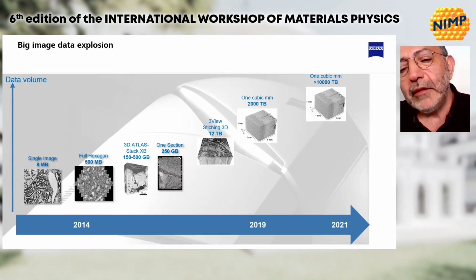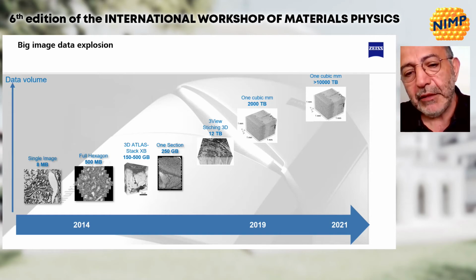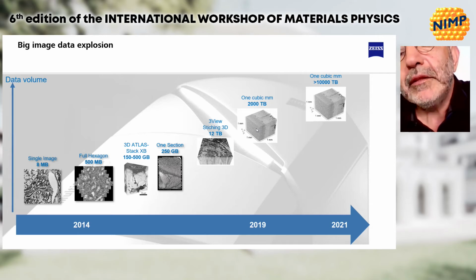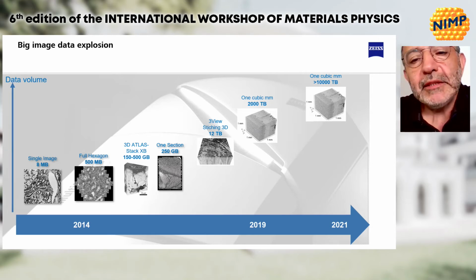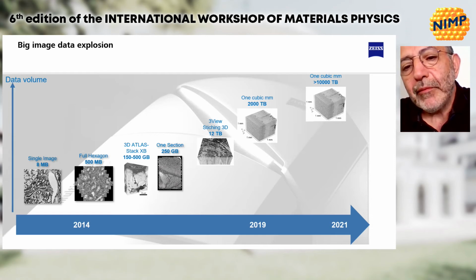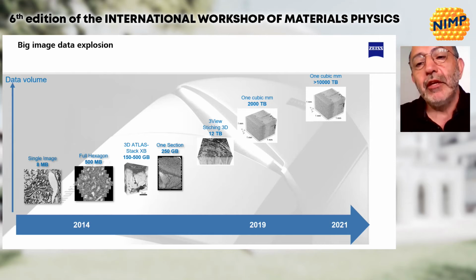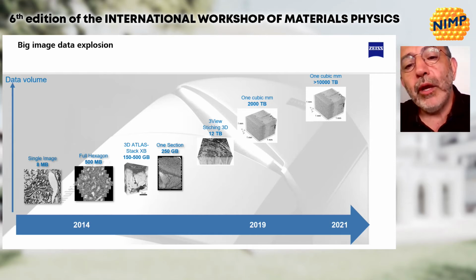This was scanned 1.5 years ago, and the reason the publication only happened a few months ago is that the scanning time of the few cubic millimeters took with the multi-SEM more or less 6 months, but the segmentation of this cubic millimeter at nanometer resolution took more than 1 year, using Google as a partner computer center for this investigation. That gives you a dimension of where we are now when we are talking about correlation of very large areas, or in the extreme case 3D cubes of matter at nanometer pixel resolution.